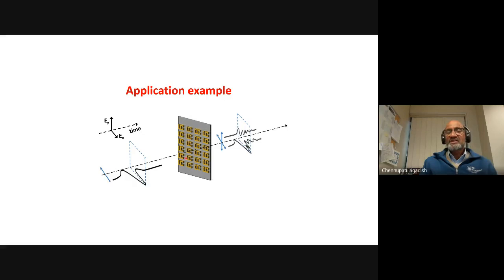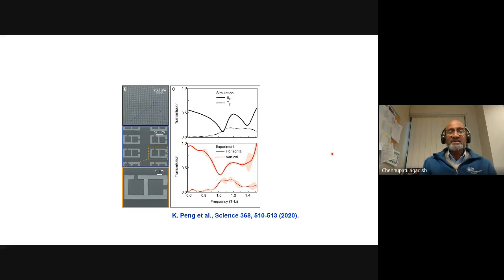Then she developed this so-called design, the terahertz metamaterials. We come up with the terahertz pulse, the terahertz pulse interacts with the terahertz metamaterial and changes the polarization, and we use our detector to measure the X and Y polarization of the modified terahertz pulse. Now we can see that these are freshly fabricated ones based on the design. You can see the terahertz transmission for the X polarization you would expect this way, and for the Y polarization it should be like this, as theoretical simulations show, and our experimental results show a very similar response, indicating that these polarization-sensitive terahertz detectors are really useful.